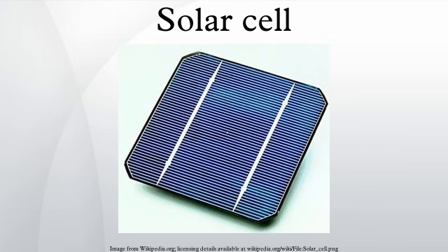This type of cell allows more flexible use of materials and is typically manufactured by screen printing or ultrasonic nozzles, with the potential for lower processing costs than those used for bulk solar cells. However, the dyes in these cells also suffer from degradation under heat and UV light, and the cell casing is difficult to seal due to the solvents used in assembly. The first commercial shipment of DSSC solar modules occurred in July 2009 from G24i Innovations.